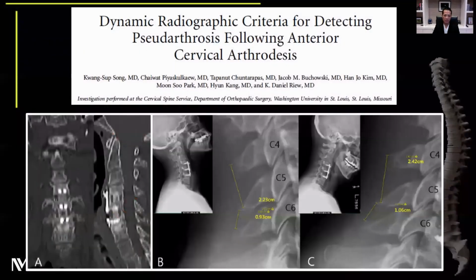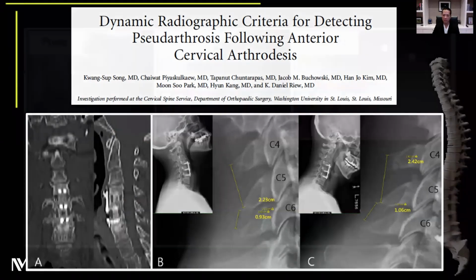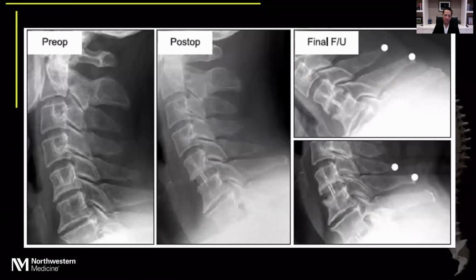The use of PEEK cages also has led to different qualifying factors to assess a fusion. On the left side here, you can see that a PEEK cage can lead to bony bridging on a CT scan, but then on the right, one can see that there is still motion within the interspinous spaces. So it begs the question, even if bone forms within a PEEK cage, are you really getting a fusion? And this indicates here that you still have motion with bony bridging with a cage.